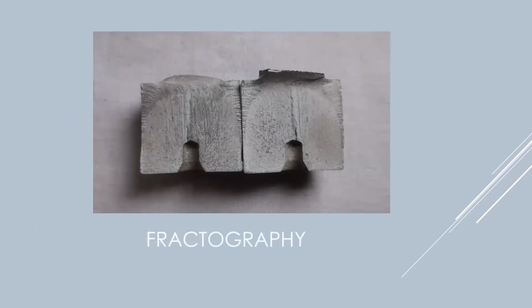We can always use in-situ replicas for fractography. Fractography means we're looking at the fracture, trying to identify the initiation site, trying to identify the damage mode, is it intergranular, transgranular, trying to identify the failure mechanism. Most of the time I would put this right underneath the scanning electron microscope, but sometimes you're not allowed to cut that piece up. This one's nice and small. Sometimes you're not allowed to cut that piece up. It could be a turbine.